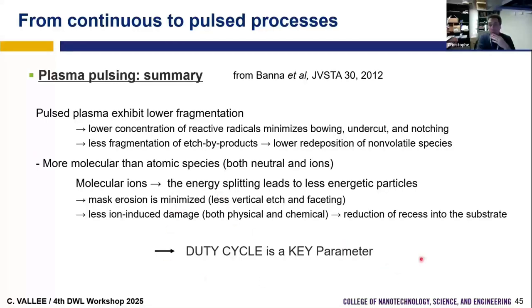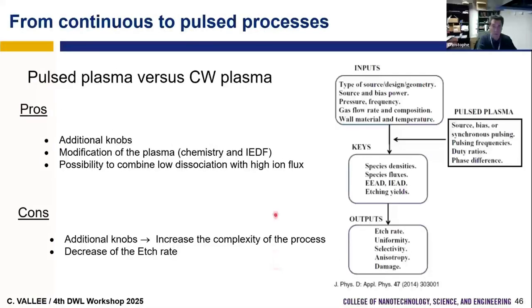And what is the most important parameter when you pulse? Usually it's not the frequency. We observe that frequency has not so much impact. Going from 1 kilohertz to 5 kilohertz is not so important. But the duty cycle is very important and has a strong impact on the plasma etching process.